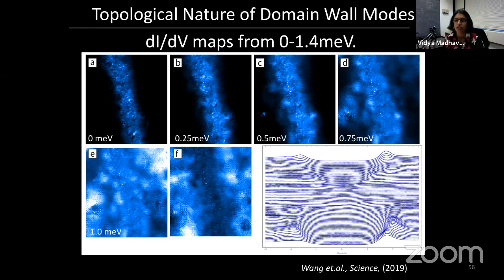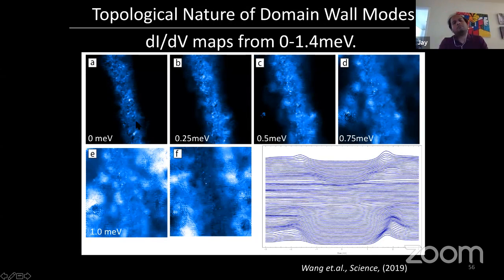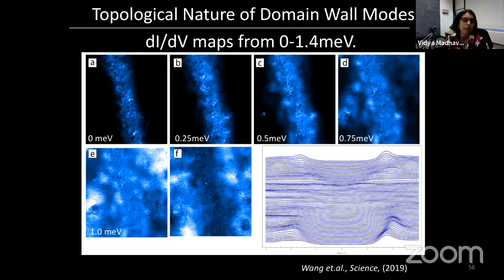You could ask if this is a simple destruction of superconductivity. One thing I would say is this observation is sort of suggestive that it's not. In fact, if I parked myself right at the edge, at the boundary, which I did earlier, and took a spectrum, it would look like a completely flat density of states. But if I park myself here, these states are no longer existent here. So I begin to see only these states, and I see two bumps. And then if I go slightly further out, the bumps actually move further along as you go further out. So there is some evidence that these are actually propagating states that live on the boundary wall rather than a simple destruction of superconductivity.